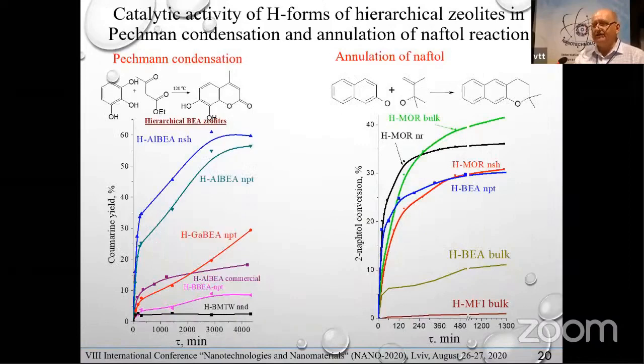The next example of high activity of such hierarchical zeolites in different processes is Pechmann condensation or annulation of naphthols. What is interesting is we can see a very clear difference between the activity of identical zeolites with identical composition and acid center concentration, but with different morphology. For example, nanoparticles of zeolite beta are usually more active than nanosheets. For mordenite, nanorods are more active than nanosheets. And in all cases, hierarchical zeolites show higher activity compared with bulk zeolites.